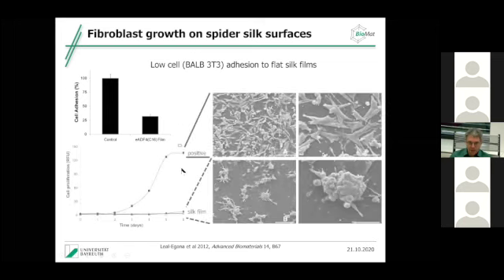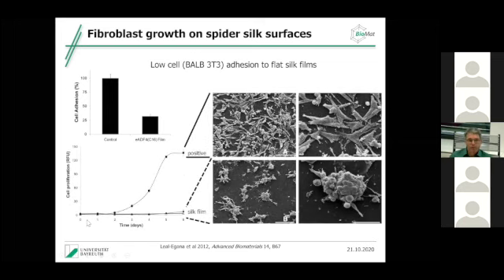We saw that the cells don't like to stick to the surface. So if you make a proliferation test, so if you look over days what happens with the cells, you see that they actually agglomerate, they still are in a spherical shape, they're not attaching to the surface, they're not spreading out, and they're not proliferating on the silk surface. But they do, of course, on the tissue culture plate.